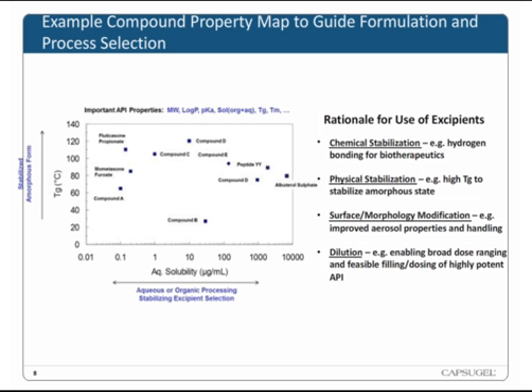And so when we spray dry these, we want to understand, okay, how stable is the amorphous state going to be? Because if the glass transition temperature is very low, the chances of being able to stabilize that in terms of it converting to a crystalline structure over time becomes much more challenging. And then we start to use this type of rationale for what types of excipients we may want to use. And we'll also use this rationale for the type of process. So if this is going to be really hard to stabilize in the amorphous state, we may use a process that results in crystalline active. And I can speak a little bit more to that in a few minutes.